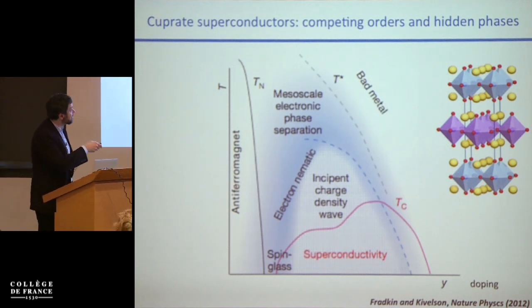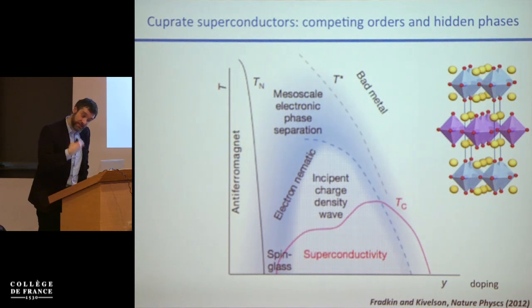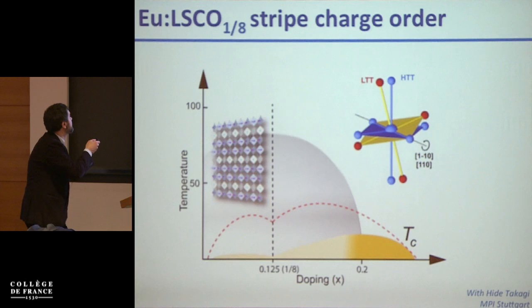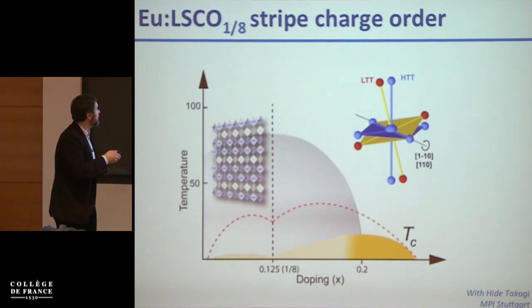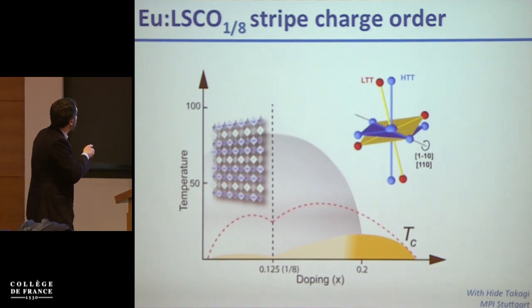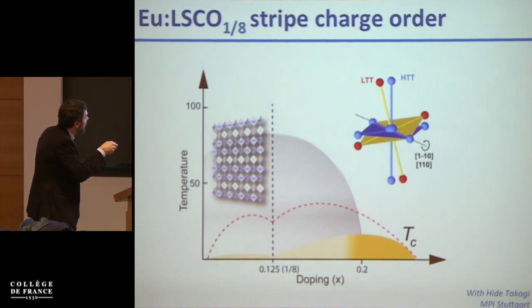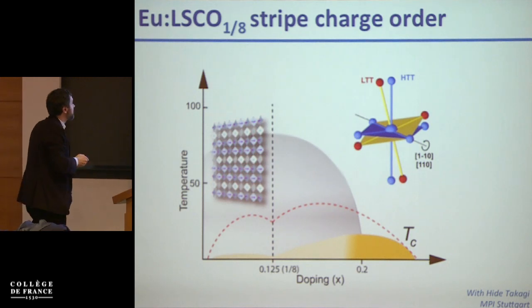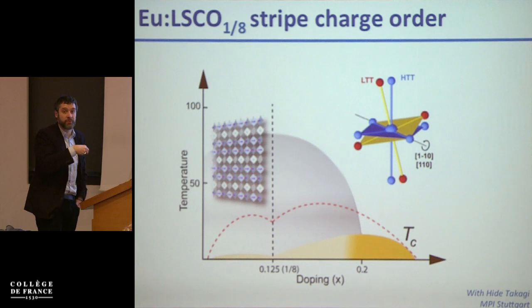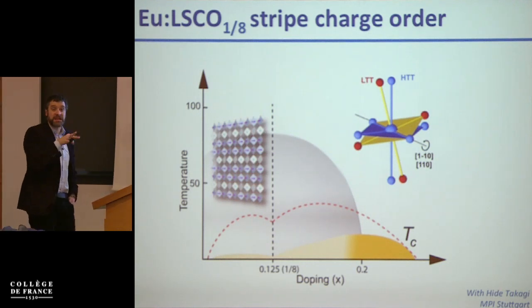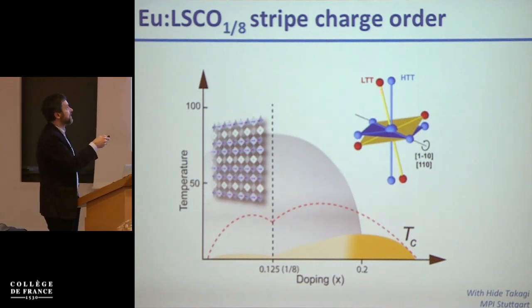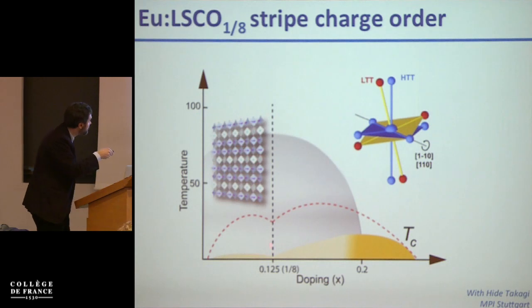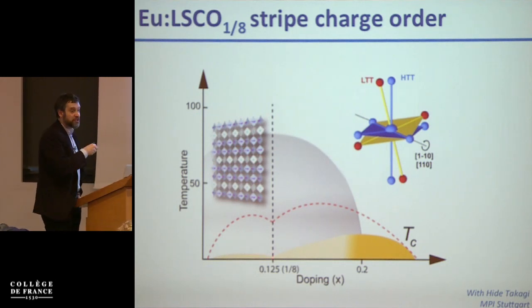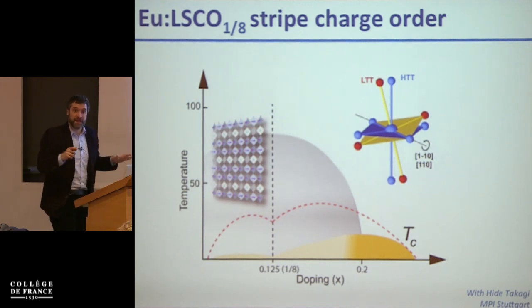And so in some cases, it's known, as I mentioned before, that these orders are actually enemies of superconductivity. This is, for example, the case in this europium-doped lanthanum strontium cuprate at 1/8 doping, in which one finds this stripe order. One particular distortion of the oxygen octahedra, which has to do with a tilting of these octahedra with the correct spatial periodicity, underpins the stripe order that quenches superconductivity. So when we started thinking about this, we said, okay, maybe if we shake these phonons right, we can take the low temperature tetragonal distortion, which down here quenches the superconducting state, and pull it straight and melt this lattice order, and then make the system superconducting.